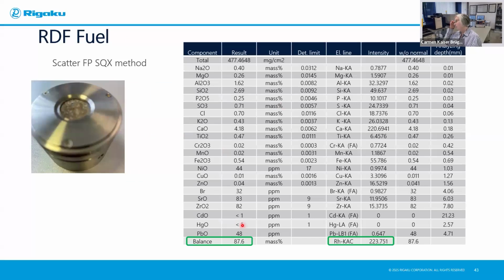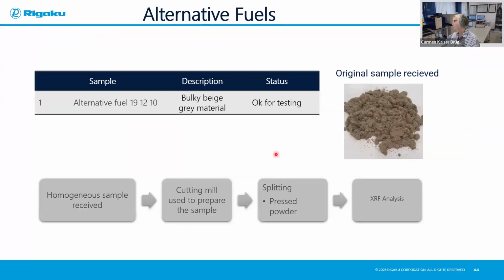And what's very nice from our software is that we get the information about the analyzing depth. So if we are looking, for example, for the zinc in the material, it's very important that the zinc that we measure here has an infinitely thick sample, because the heavier elements, like you can see here, have a deeper penetration into our sample. So we need to have a thick enough sample for the analysis. So this is why our software is so beneficial for getting the correct analytics for our alternative fuels.